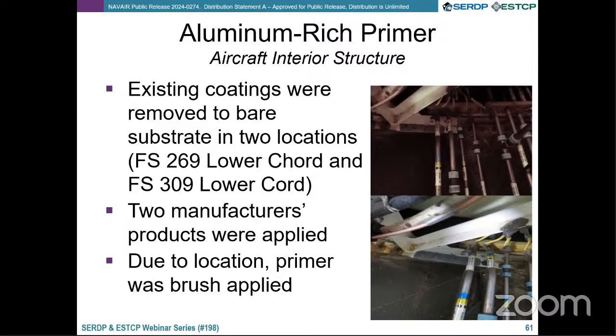And you see there, I know the pictures are a little difficult, but this is a lower fuselage primary structure area called a chord. As you can see there where we've applied the primer, it's an area at the bottom of the belly of the aircraft, and it's expected to gather water, oils, and other contaminants, and it's been a challenge to protect against. So we brushed the primer onto areas that had their corrosion removed.